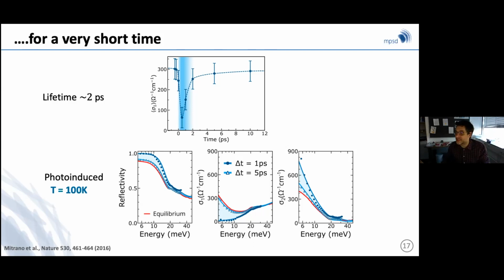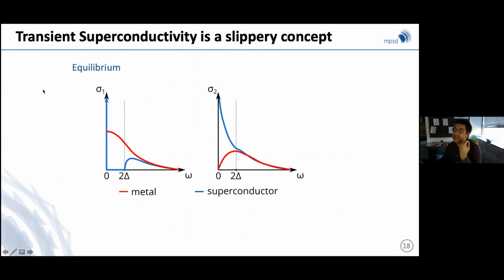Okay, we could belabor this a little more later. But this creates all sorts of trouble, and also the fact that transient superconductivity, you can see that I've been conditioned by a lot of conversations with the referees. Transient superconductivity is a very slippery concept because at equilibrium, I can think of a superconducting state in which all the spectral weight, say sigma 1 in this metallic state, is squashed to zero frequency in a delta function, which is then reflected by a divergence in sigma 2. The moment I make the lifetime of this state shorter and shorter, this delta function will broaden up to a frequency which is basically the inverse lifetime.